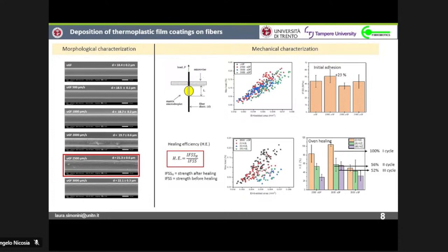Still from this set of data, we evaluated the healing, providing the healing by placing the samples in an oven. And we obtained at the first healing cycle 100% healing efficiency. So we were able to fully repair the interface. Then we did two other cycles of breaking and repairing, and we obtained 50% of interfacial healing.